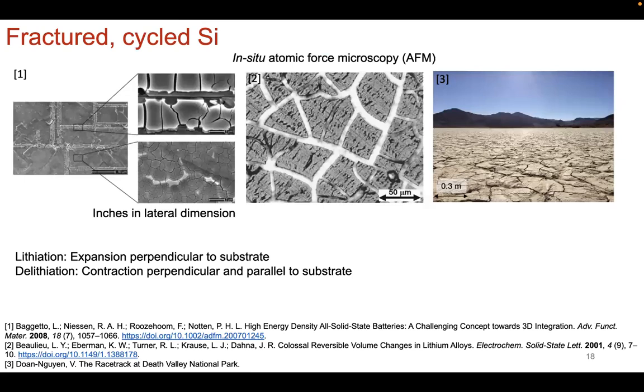And that's motivated by the fact that we just saw the electrochemistry is not promising in the sense that the capacity fade is high, right? You have trapped lithium ions, which you don't want. And on top of that, the mechanical integrity of your electrode fades rapidly. So this has been seen with a number of thin film studies. So you see that here, that you have a thin film of silicon, and upon lithiation and delithiation, you basically introduce cracks, and that's what you see.